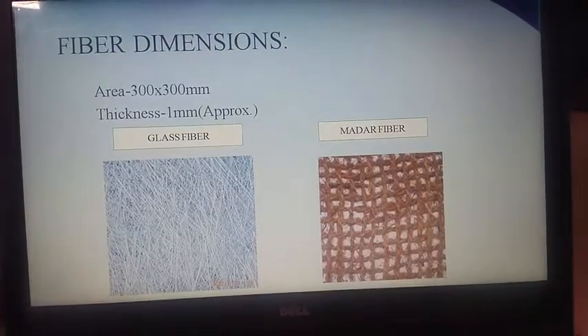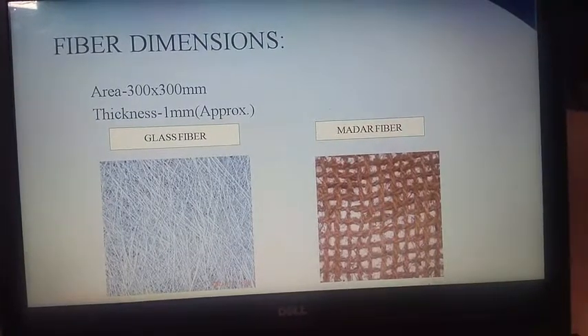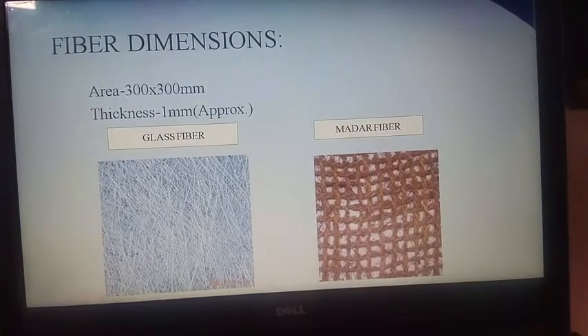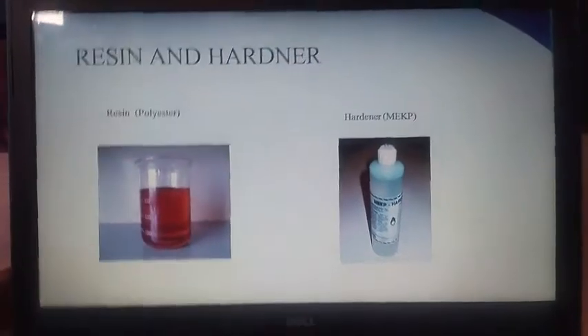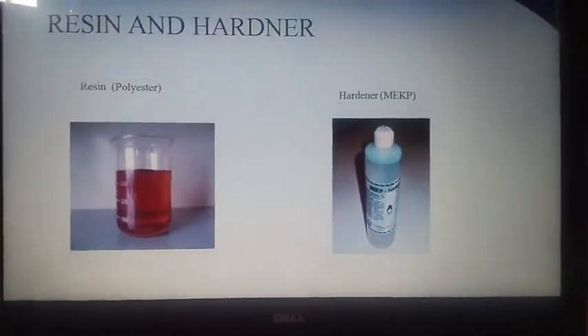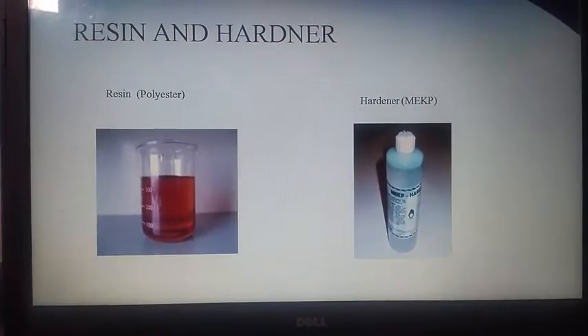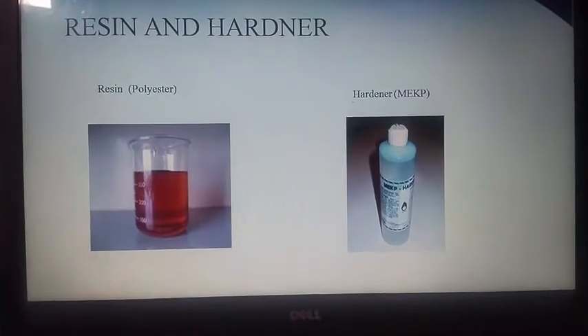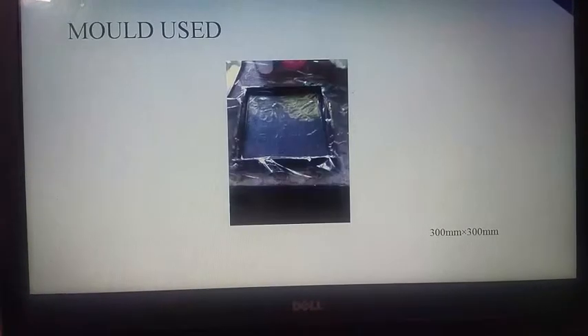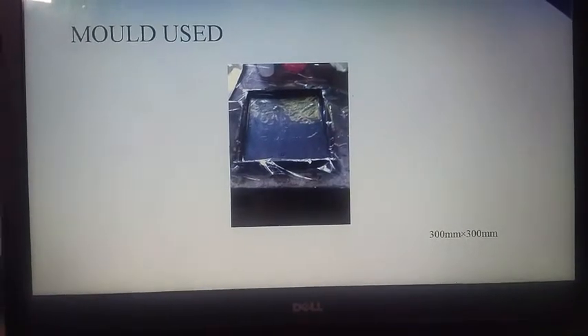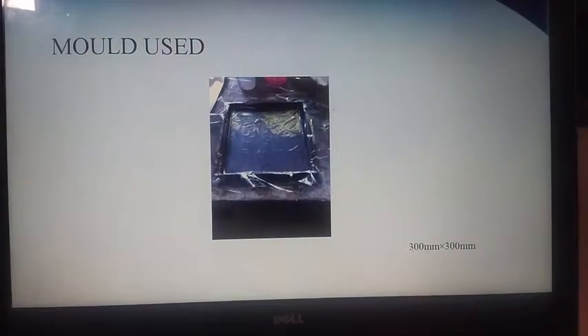These are the fibers, glass fiber and Madar fiber. The thickness of them is approximately 1 mm. These are the resin and hardener. The hardener is MEKP, that is methyl ethyl ketone peroxide, and the resin is polyester. This is the mold we use to fabricate.